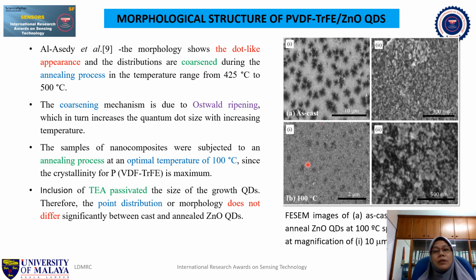So from this picture, we can conclude that the nanocomposite is not affected so much by the annealing temperature of 100 degrees Celsius because in this experiment, the zinc oxide quantum dot is passivated by TEA, which prevents the growth of zinc oxide quantum dots. So the particle distribution or morphology from this picture does not differ significantly between the cast and annealed zinc oxide quantum dots.